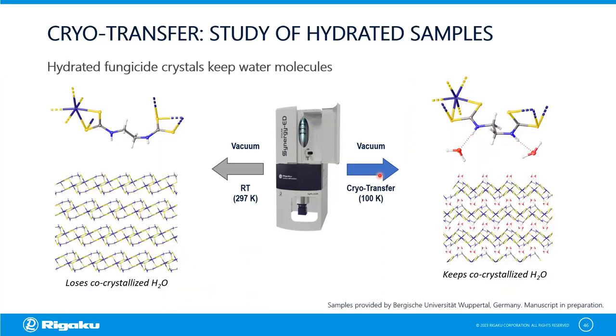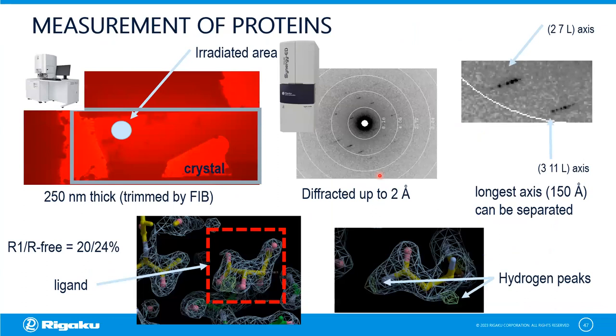And a second example is a hydrated fungicide here. In both cases, we get good diffraction and a good structure from both, but you can see that the actual structure of the material is quite different depending on whether it's hydrated or not. And the ultimate example of a hydrated sample is a protein. So in this case, Ito-san and Yamano-san took a thaumatin crystal, went over to our colleagues at JEOL in Akishima, put the grid in a focused ion beam system, produced a thaumatin crystal that was only 250 nanometers thick, then cryotransferred that to the Synergy-ED and collected data up to 2 angstroms.